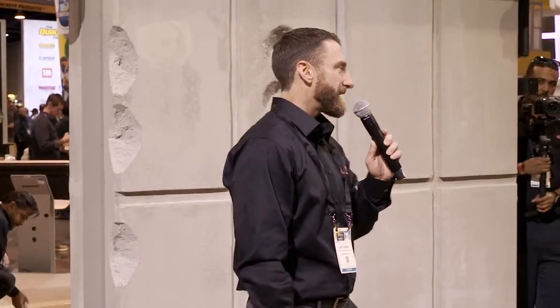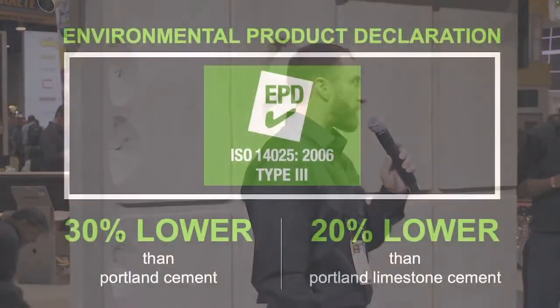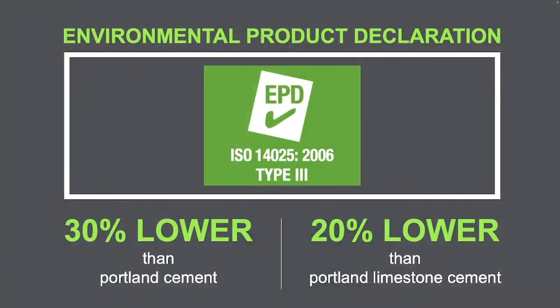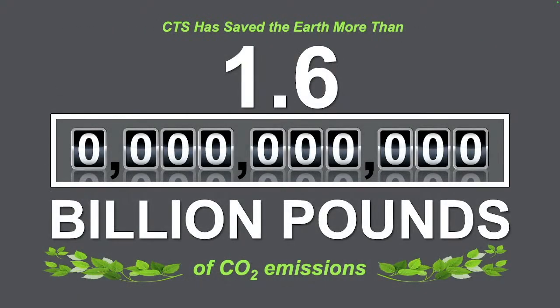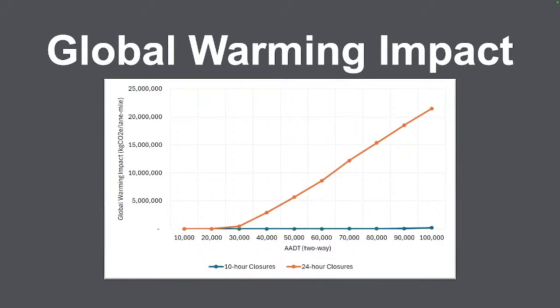And finally, the global warming potential of Rapid Set cement is about 30% lower than that of Portland cement and about 20% lower than Portland limestone cement. And that's because of our chemistry differences and the fact that we can burn at a lower temperature. Well, these numbers are documented in our Environmental Product Declaration, or EPD, which is a certified third-party accounting of cement manufacturing impacts. And what this means is CTS has actually saved the Earth over 1.6 billion pounds of carbon emissions over the life of the company.